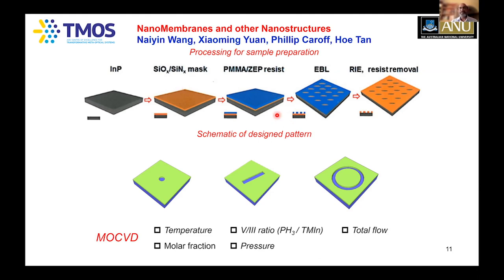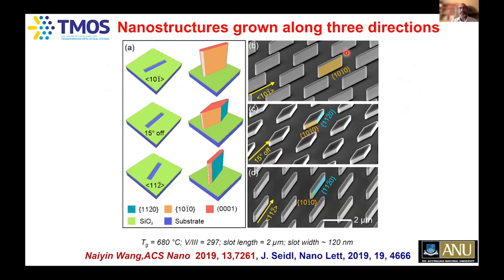This particular work has been associated with my colleagues, whom I have listed here as well. So here is a case where the slot is opened along a particular crystallographic orientation, and this is put into the epitaxy reactor and again heated up to 650 to 750 degrees Celsius, and the gases needed for the growth of indium phosphide are introduced. You can see you can create these beautiful nanomembranes of indium phosphide with these sidewall crystal facets.